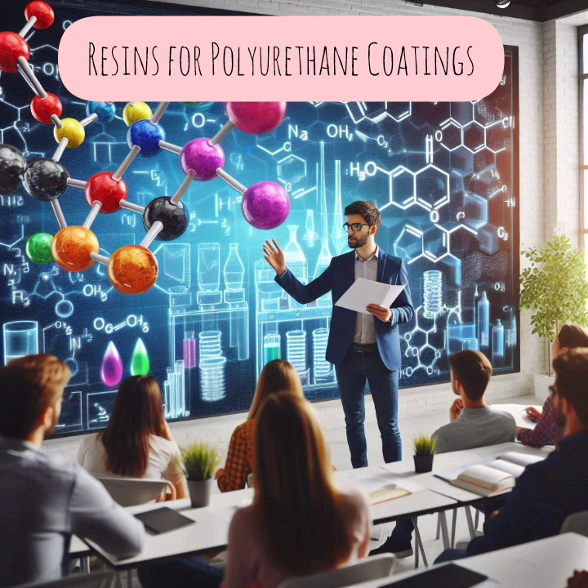The reaction initially produces an unstable carbamic acid, RNHCOOH, which decomposes to a primary amine and carbon dioxide. This reaction is exploited in the case of urethane foam formation and avoided in the case of urethane coatings. Hence, systems to be reacted with isocyanates for coating purposes should be dehydrated, and low moisture content urethane grade solvents should be used. Polyurethanes are capable of providing very tough finishes with excellent resistance to weather, corrosion, abrasion and chemical attack. Films can be made flexible enough to coat rubber, leather and plastics, and hard enough for metals and concrete.